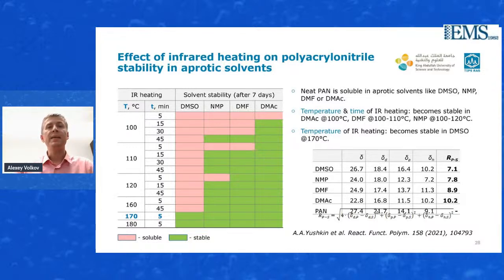Well, that's data on the stability of the membranes which we prepared and modified by infrared. And as we can see here, we can start with 100C for 45 minutes of treatment, which gives us already stable membranes in dimethyl acetamide. But if you'd like to improve the stability, then we need to increase the temperature or the exposure time. And actually at 170C and 5 minutes of treatment, the membranes are stable in the most common aprotic solvents used for membrane fabrication.